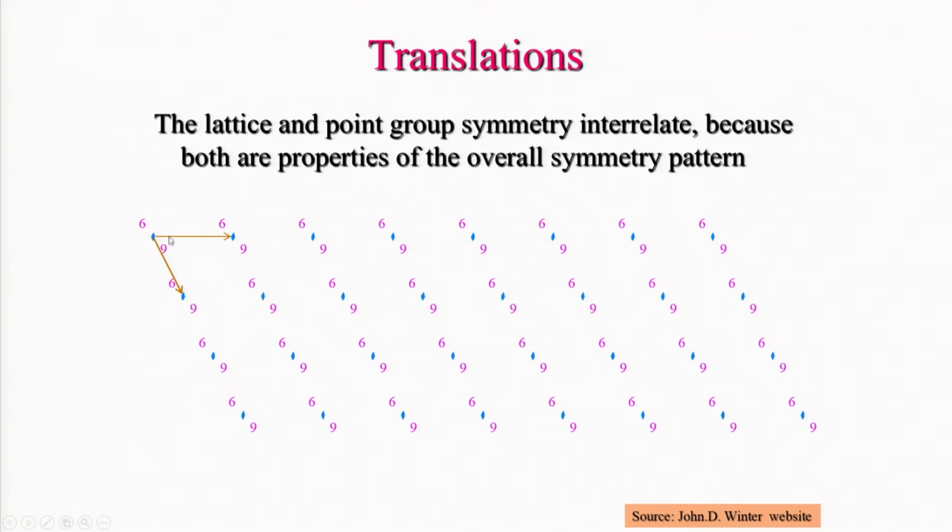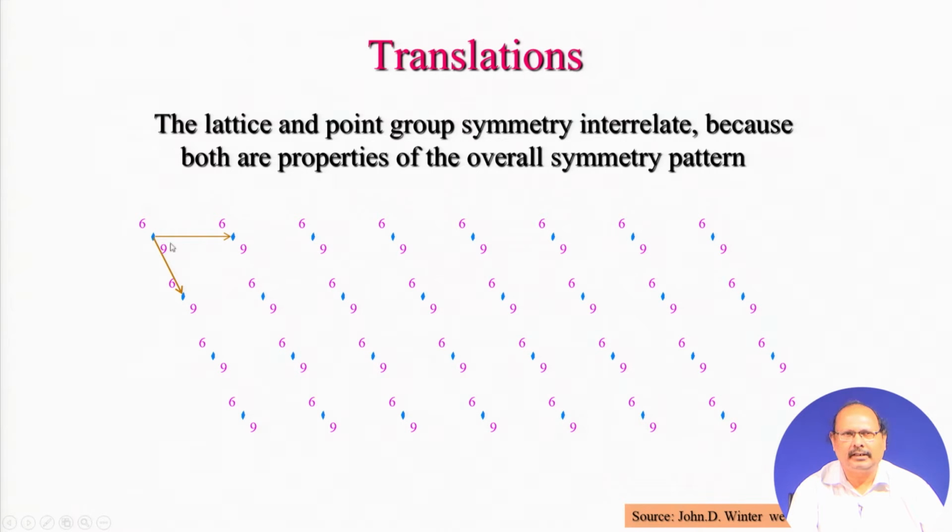For example, if you have a two-fold axis, or diad, then 6 is rotated 180 degrees and produces another motif, say it will look like 9, and this will be translated along the same a direction, and it will produce this pattern, 9, and this pattern 6 and 9 can be translated along this direction, and we develop the whole 2-dimensional geometry of this crystal. The lattice nodes and the point groups of symmetry are interlinked.